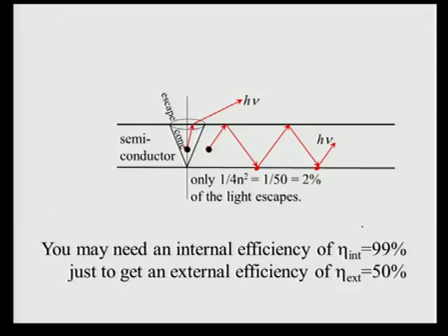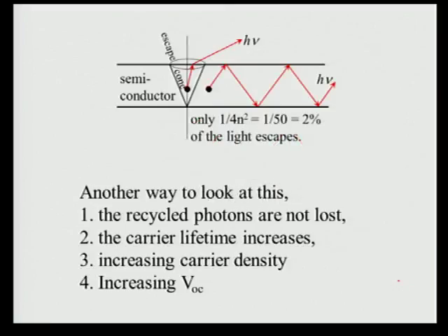It has to be a material that has 99% luminescence efficiency. Indeed, you may need 99% luminescence efficiency just to get 50% out because of all the bouncing and all the reabsorption. There could be 50 reabsorption events. So it's very, very challenging.